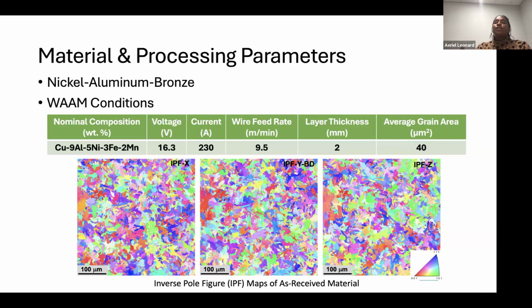Before we take any samples, we go through the thickness of each printed bar to get a sense of how the microstructure changes through the thickness and along the length of the bar, so that we understand how these microstructures will influence the mechanical properties. It's really because of the nature of AM. You're reheating and remelting layers, and so you're getting different heat affected zones. Solidification rates may change because of this reheating and remelting.